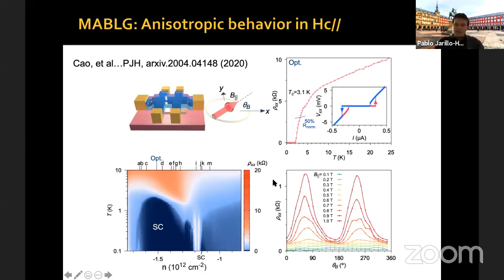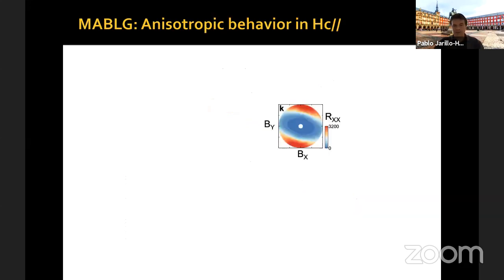Okay? Now, if you measure the resistivity as a function of parallel magnetic field magnitude and orientation in plane, you see that we have these two maxima. Okay, two maxima means, again, twofold symmetry. It means an ellipse in polar coordinates. Okay, let me show you the actual ellipse. So this is, again, resistivity as a function of magnetic field in the X and Y direction. You can see that there is an ellipse, which means the system exhibits very different critical field when your field is oriented along this direction and when your field is oriented along the perpendicular direction. You have an ellipse, okay?